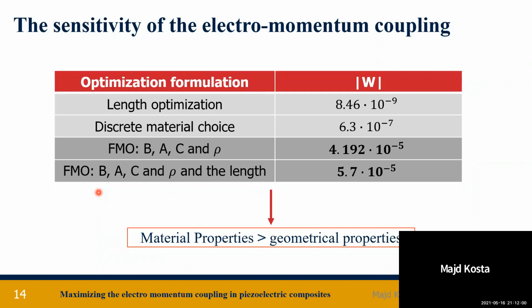Now, to examine the sensitivity of W, we applied once again FMO, but now with a fixed, equally divided periodic cell. And we can see that both results are close to each other, which means that optimizing the electromomentum coupling is more sensitive to the material properties rather than the geometrical properties. This can be seen in a comparison between these two lines.